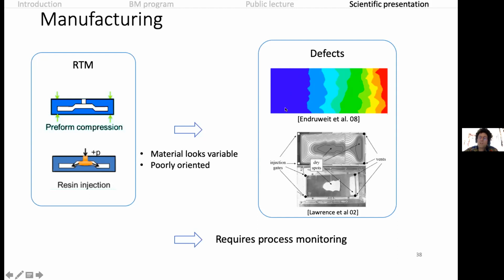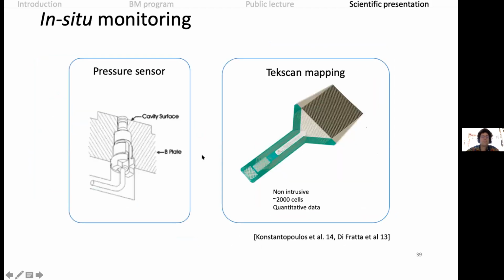One way to monitor this process of resin infusion inside the preform is to put some pressure sensors. And that's what we did during my 3-month stay. We used this commercial pressure sensor instrument. So this is a film made of almost 2,000 cells that we barely see here, but there's a lot of cells here, and this gives the pressure at each location in this 10 centimeter by 10 centimeter film. We're going to put that inside a mold and try and see what we can do with that.